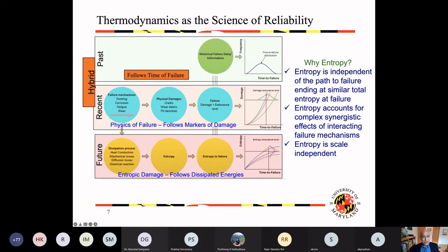So in order to alleviate that, the new trend in reliability originated in the 1960s and then picked up again in the 1980s as physics of failure, which essentially followed markers of damage. Essentially what it did was take these physics as failure mechanisms and put an empirical model on those, for instance fatigue or corrosion, to accumulate damage, and finally how much endurance a component has over that damage, and once that endurance is reached, a failure occurs. So instead of a distribution, it follows the amount of damage from time zero based on some empirical models. And then once it found a level of endurance, you find the times of failure from those points. And then a distribution is built based on those points rather than the historical data that we gathered from the past.